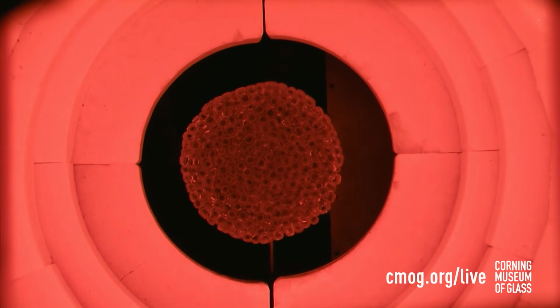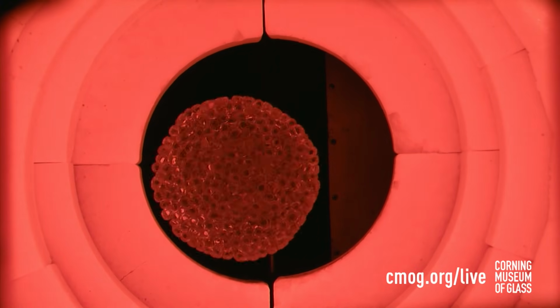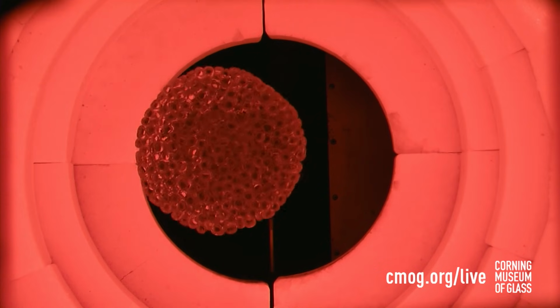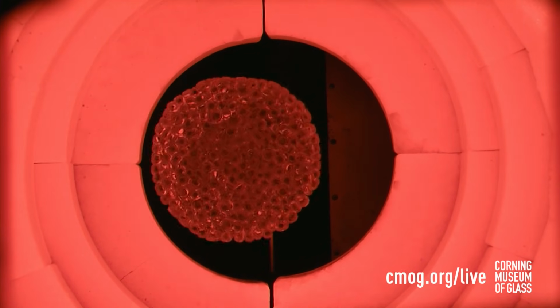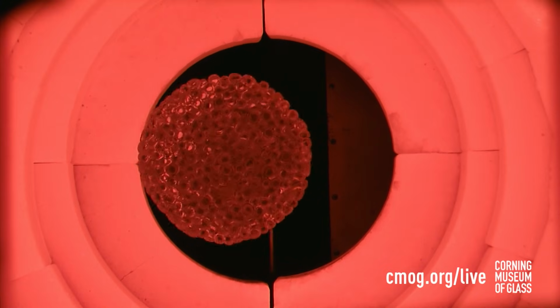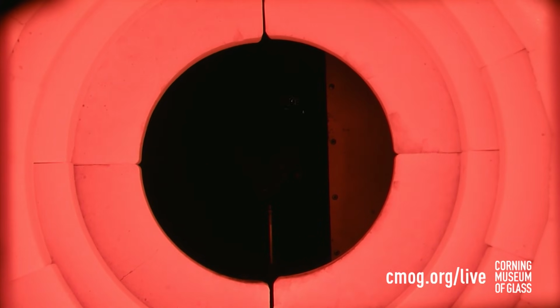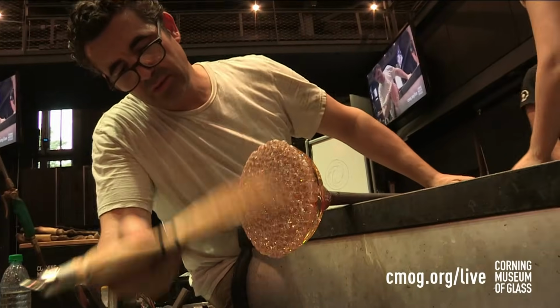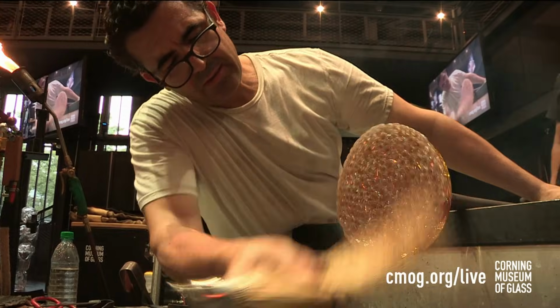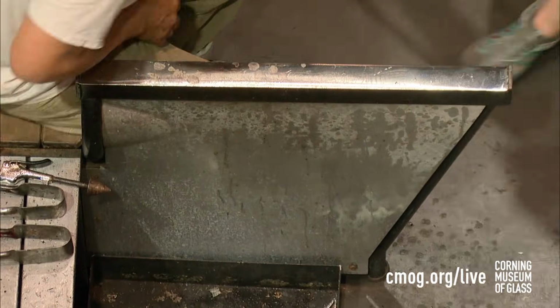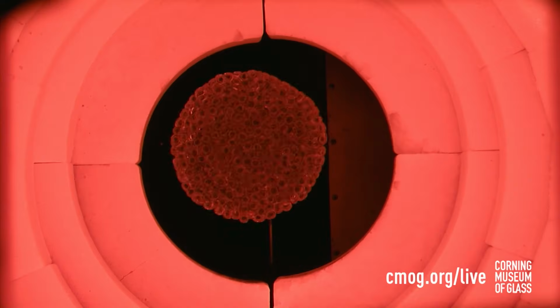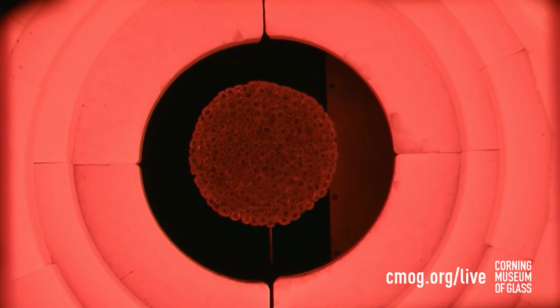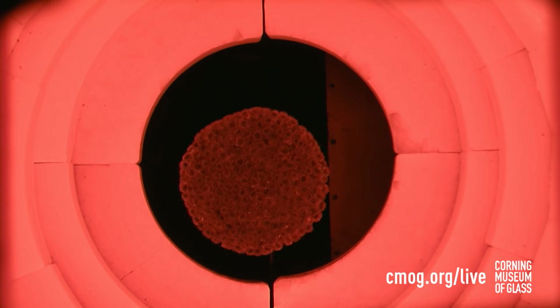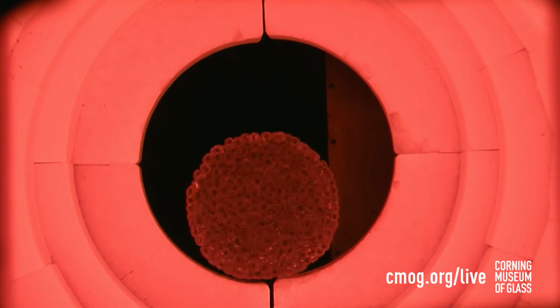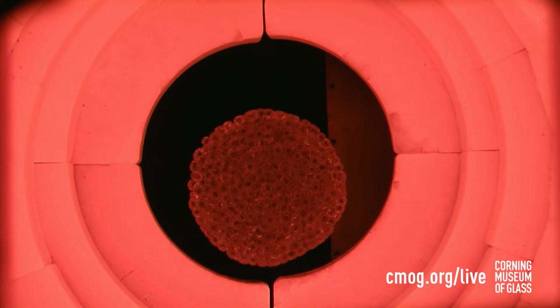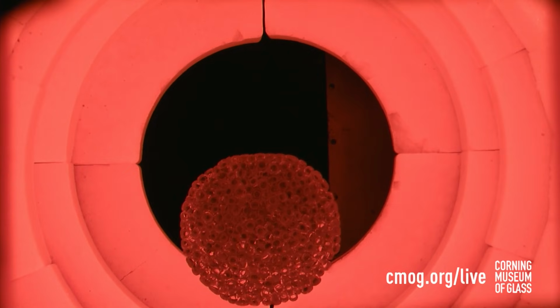Does the quality of our glass decrease using nuggets versus batch? No, it doesn't. And it's made to be reheated again that second time. You can change the quality of your glass by how hot you cook it or how long you cook it. So if we have our melting tank turned up too high while we're charging and we leave it on too high for too long, you can actually cook out some of the ingredients. Most importantly, the flux. The flux in glass tells the glass what temperature to melt at.